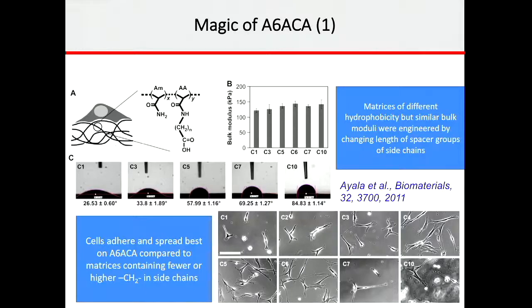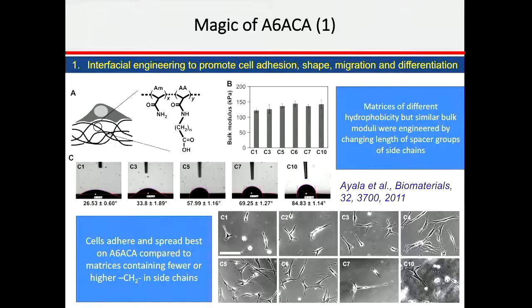So the magic was felt in many different ways. There were studies that have been done where the interfacial engineering to promote cell adhesion, shape, migration, and differentiation has been looked at. And they created matrices of different hydrophobicity but similar bulk moduli. And they were engineered, and the length of the spacer group was changed. And you can see very clearly that C5, that means acryloyl 6-aminocaproic acid, is the one where there is maximum adherence.